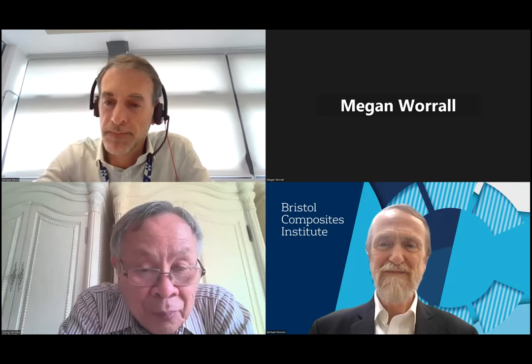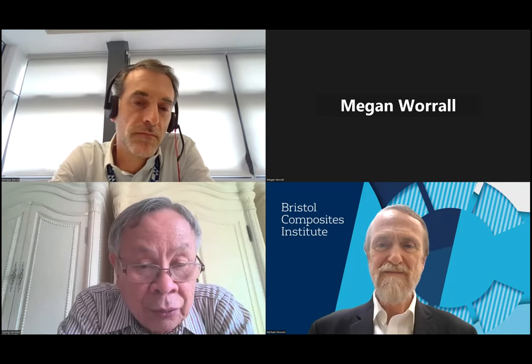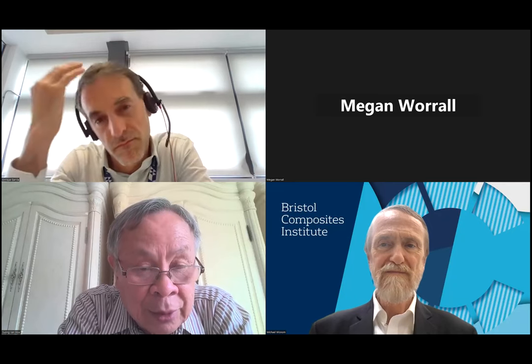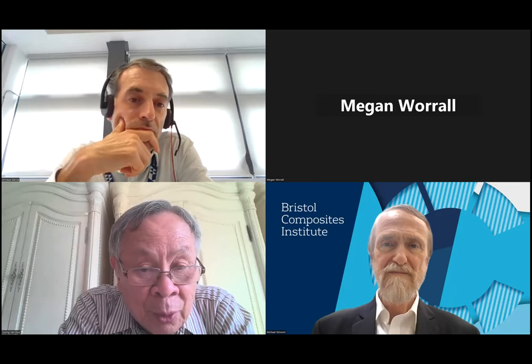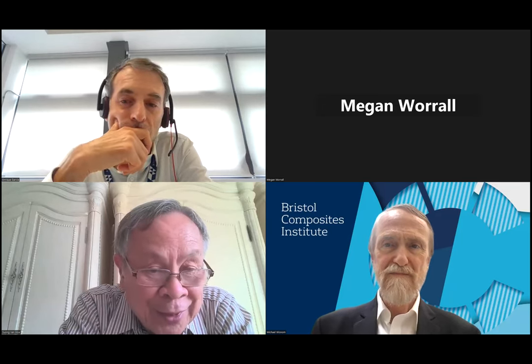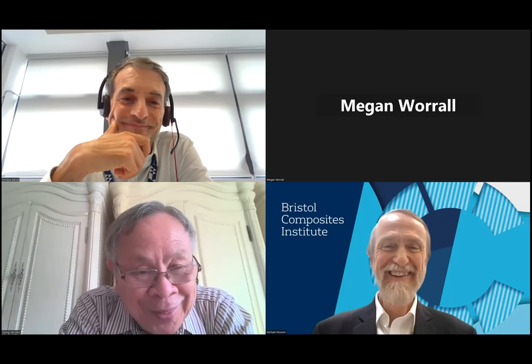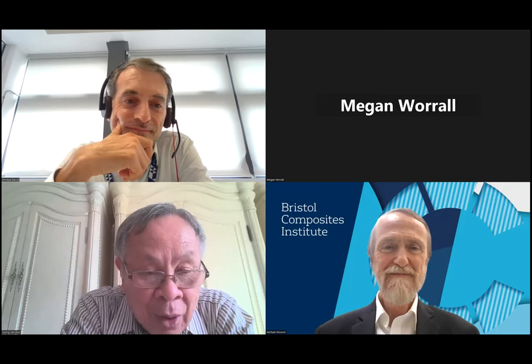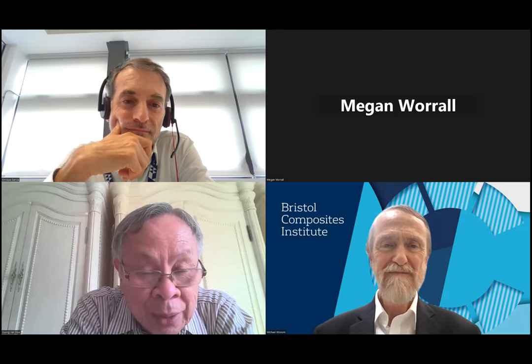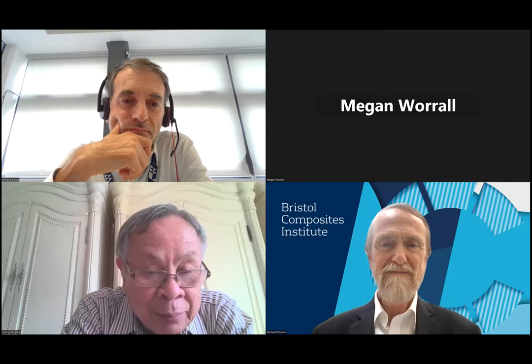Well, so far, we have made some structures that consist of changing from convex to concave. So if the inflection point, like we made a stiffener for aircraft, and also recently we made a cone, a conical shell, using the 4D printing method. If you want to know how to make it, I will give a presentation at ICCM at the end of the month about that. But the doubly curved surface, we have not done. We have done single curvature, taper like the case of the cone, and also, like I said, the change from convex to concave as well. We have not tried out the double curve surface. We need to find some kind of structure that may do that.